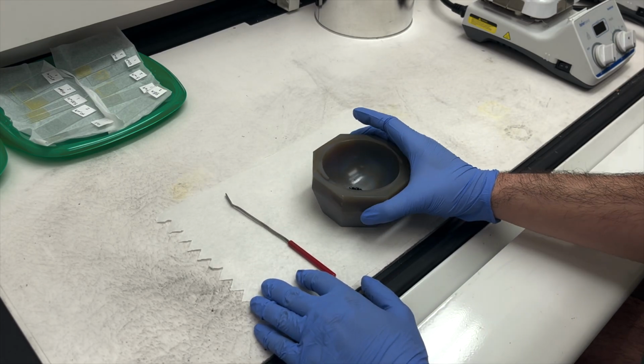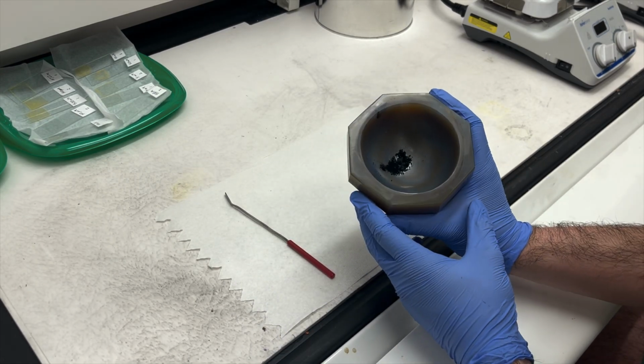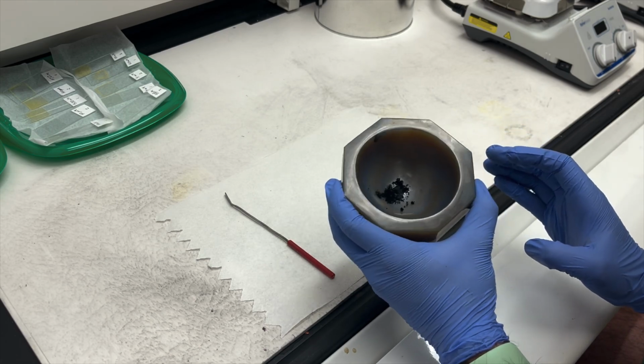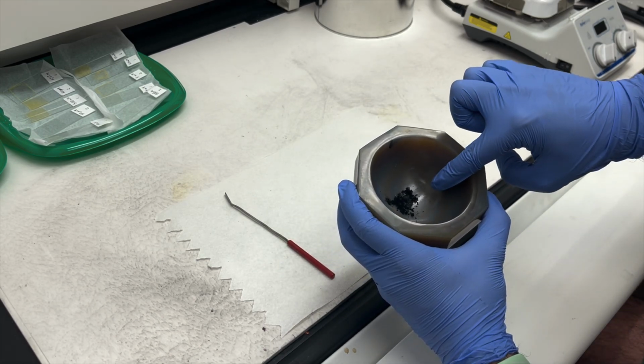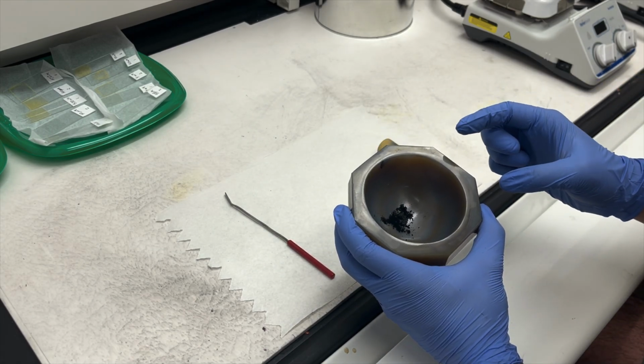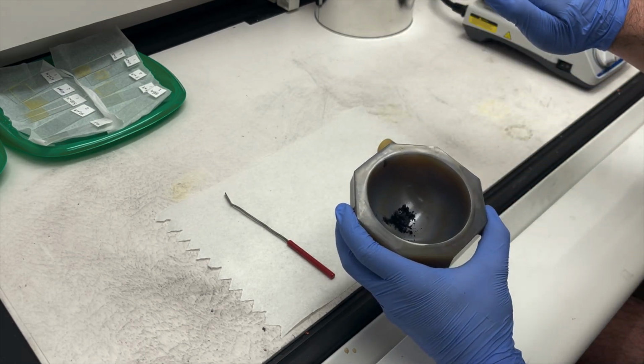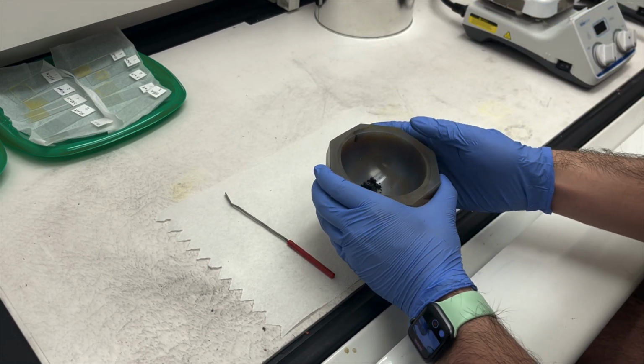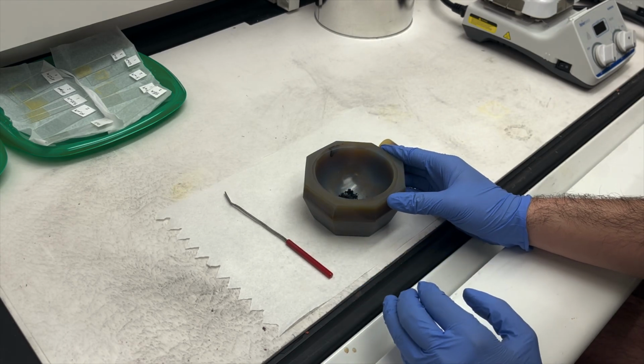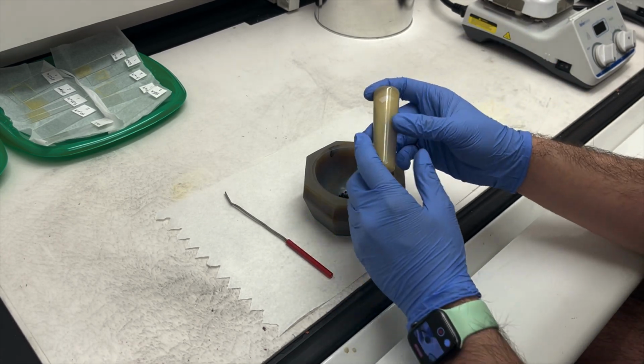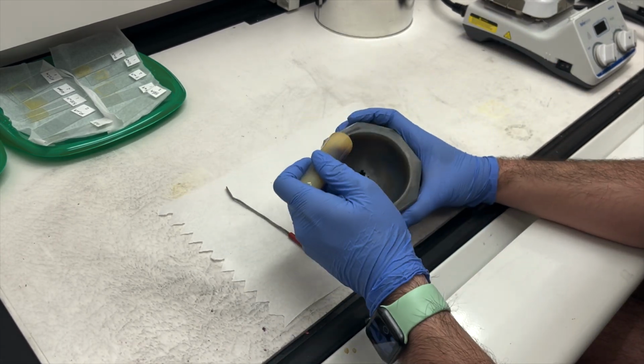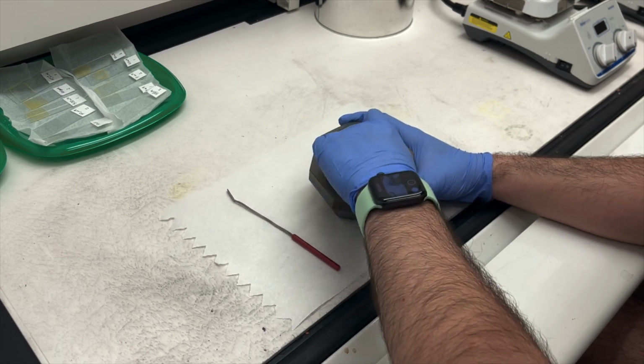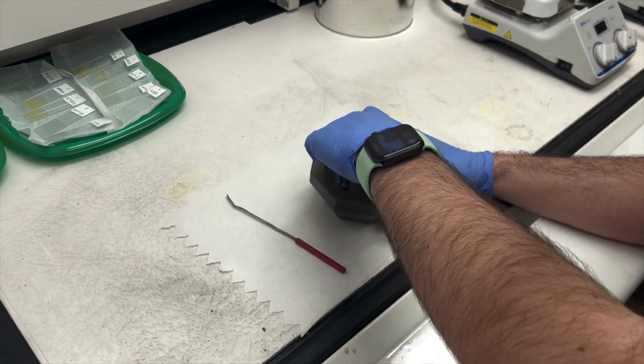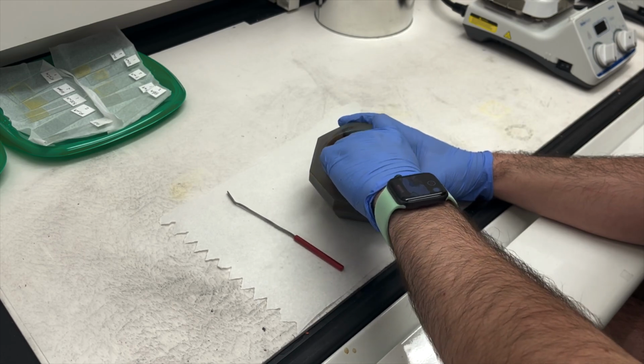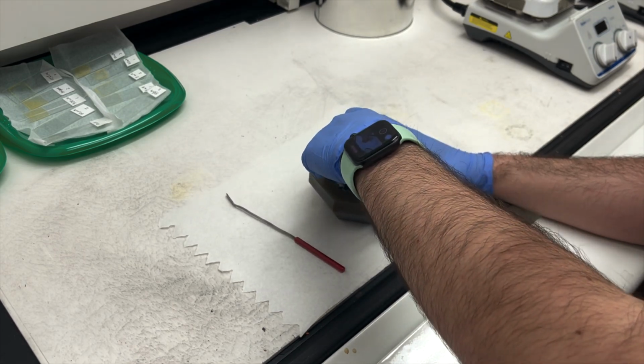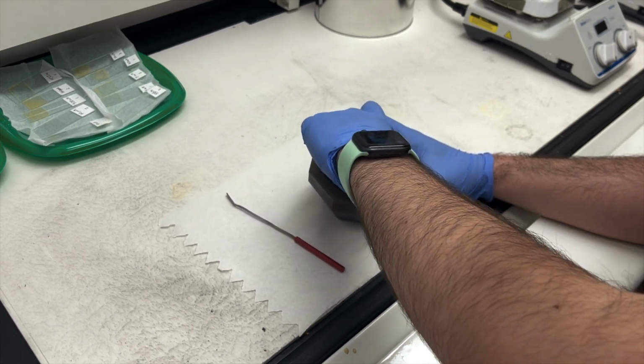Having transferred the powder from the table into the fume hood, you will then begin grinding the two powders together. Here I'm pointing out that the color of the powders is not quite the same, and what I'm getting at there is that it's important for these powders to be uniform. When we get to the slurry deposition, we want to have a thin, homogeneous film. If we don't get that thin, homogeneous film, then the properties of our device are not going to be as good.